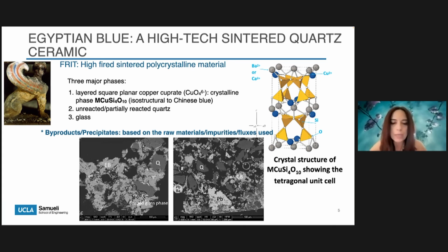Besides these major phases, this highly heterogeneous pigment also consists of other crystalline and amorphous phases, which are associated with the pigment's production. This is often at submicron level. They could be byproducts or precipitates, resulting mainly from the excess of silica, calcium, and copper oxides and excess of alkalis that were used as raw materials. These are very important, and this is what is emphasized in my talk today, as they could hold the key to a series of interconnected processes on the pigment's production technology and also materials variability.